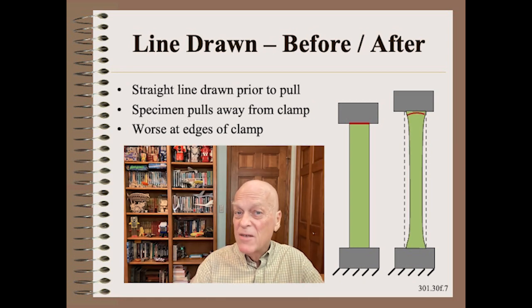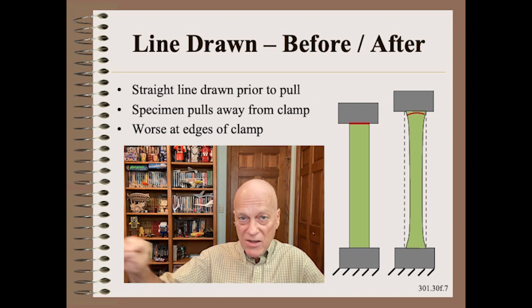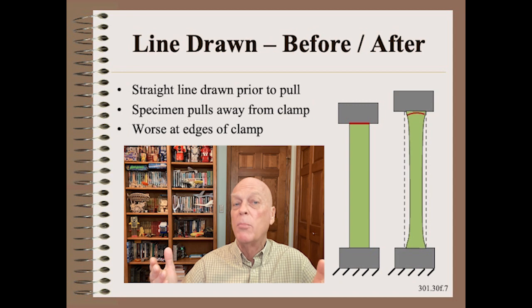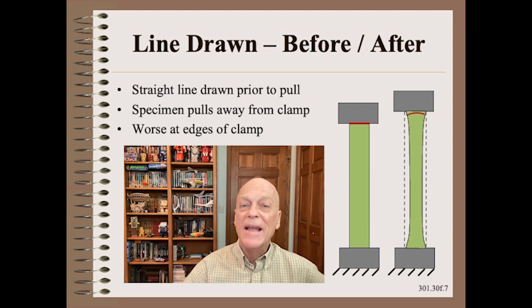To check my suspicions of slippage inside the clamp, I drew a line on the specimen at its boundary with the clamp prior to the pull. After the pull, it was easy to see the specimen pulling away from the clamp and that slippage was worse at the edges.